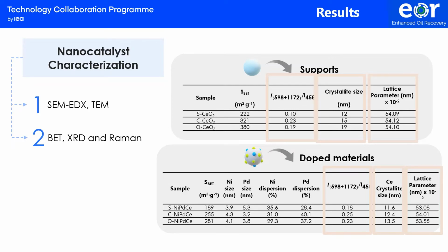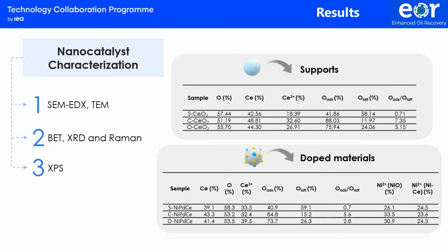Also, the concentration of oxygen vacancies increases after the doping process due to the increase in effect size by the nickel and palladium ions. From the X-ray photoelectron spectroscopy results, it is noted that the oxygen ratio ascribed to surface versus lattice oxygen increases in the order spherical, orthorhombic, cubic nanoparticles.